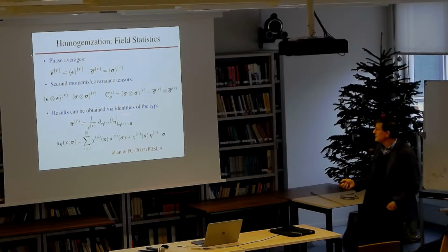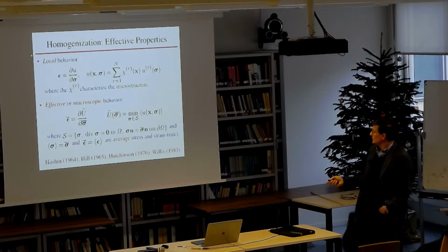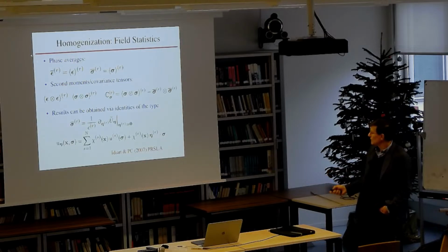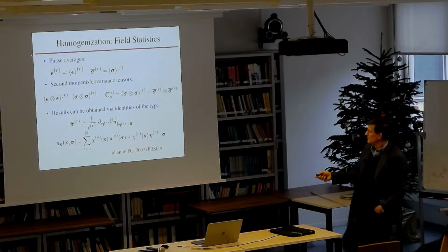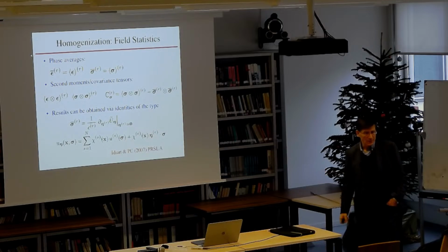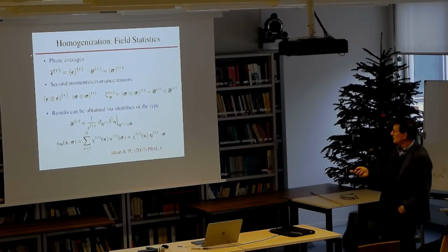And there are some identities that you can use, for example, to compute the average. Remember that this is a nonlinear constitutive behavior, right? By basically making use of results of this type, but with perturbations, you perturb the result through, in this case, something that is linear in the stress, and by solving that problem for that fictitious material with the perturbation, you can then get an estimate for the average of the stress in phase R by taking derivatives with respect to the corresponding parameter. So that's what we can do.